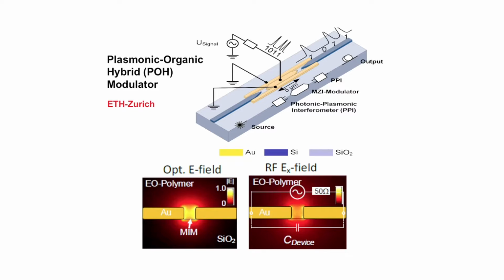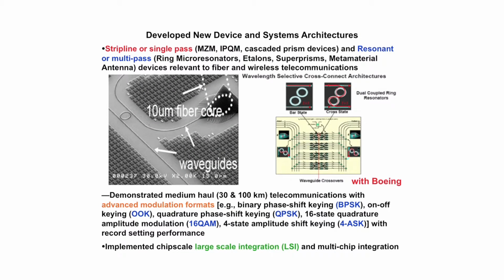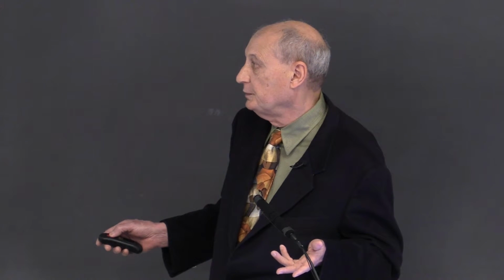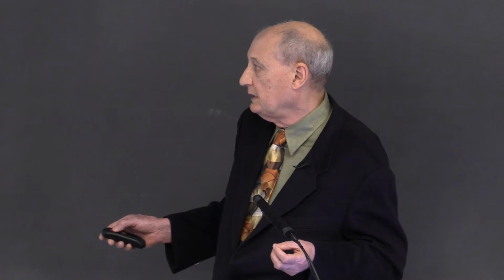And what you have here is light being brought in a silicon waveguide being converted into surface plasmon polaritons through this region of a metal-insulator-metal device where the insulator is organic electro-optic material, and then back converted to a photon. And the information or signal is encoded by applying a voltage and perturbing the phase of the propagating surface plasmon polariton. Again, you note that you're concentrating both optical and low-frequency electrical fields in these nanometer slots. When I say low frequency, you realize this ranges from DC up to about 30 terahertz, so it's a pretty broad range. But of course, optical fields are much higher frequency.